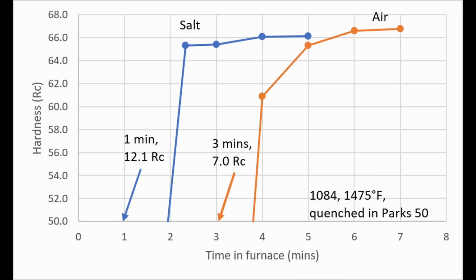With 1 minute, it was still 12 Rockwell, so not heated up, and when I pulled it out to quench it, I could tell it was not the same temperature as the salt. So somewhere around 2 minutes or so, it was heated up. When I did the same thing with air, even after 3 minutes, it was still 7 Rockwell. It had not heated up sufficiently.